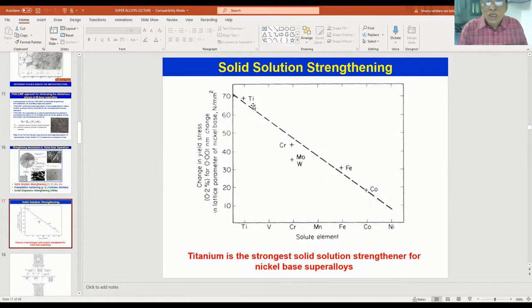It provides solid solution strengthening to the matrix. It provides gamma prime, the major strengthening phase. It also participates in carbide formation. So we should be very careful in choosing each element. Since partitioning for these phases will be occurring, we have to carefully choose each alloying element, how much it should be present in the material.